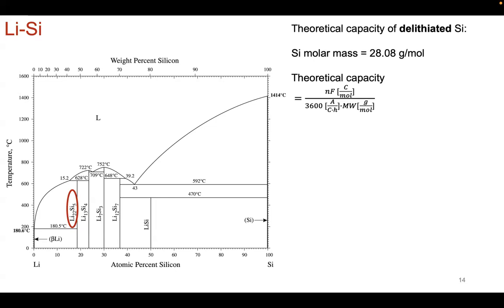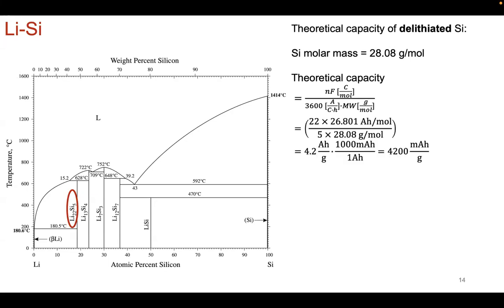Now, what you have seen in terms of the theoretical capacities that have been reported is usually for the delithiated phase, right? So a review of the theoretical capacity and how we calculate that: it's N, the number of moles of lithium, or equivalently moles of electrons, times Faraday's constant, divided by the molecular weight of the active material. In this case, if we consider delithiated silicon, then we take into account that silicon's molar mass is 28.08 grams per mole, and that gets us the number that is 4,200 milliamp-hours per gram that you see cited quite often.